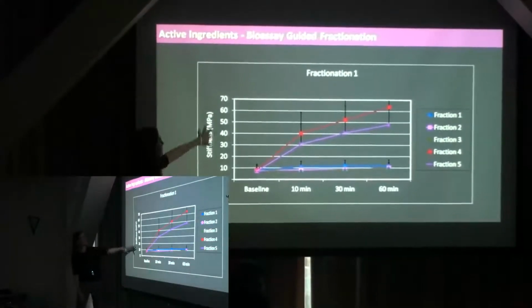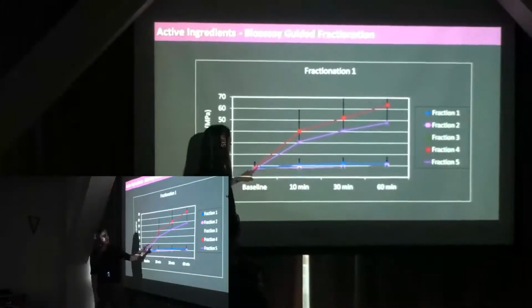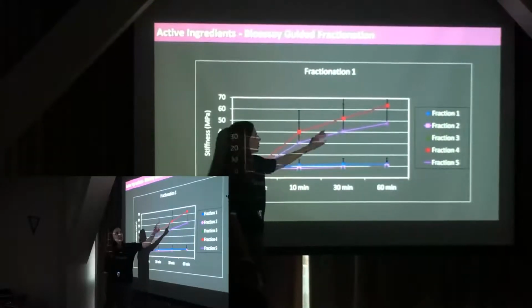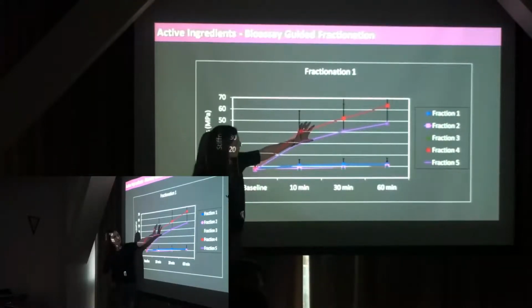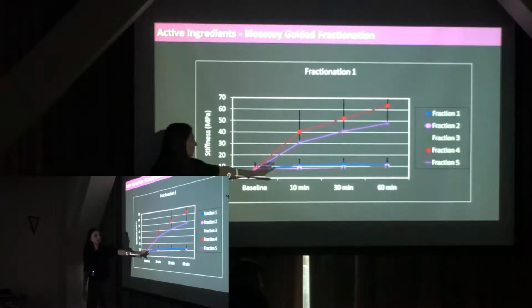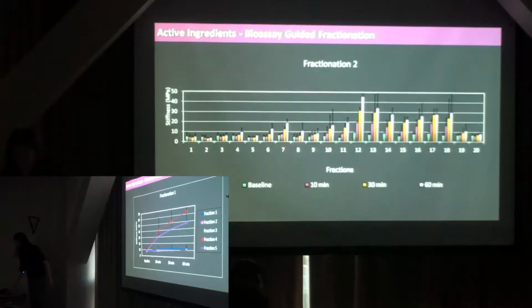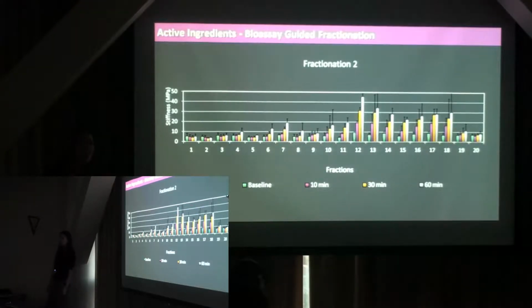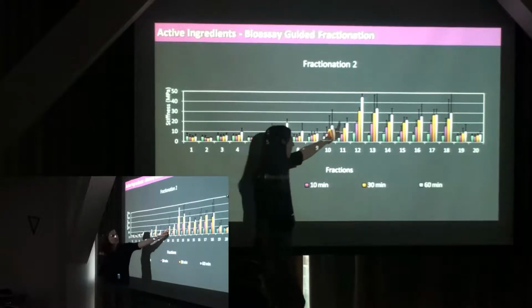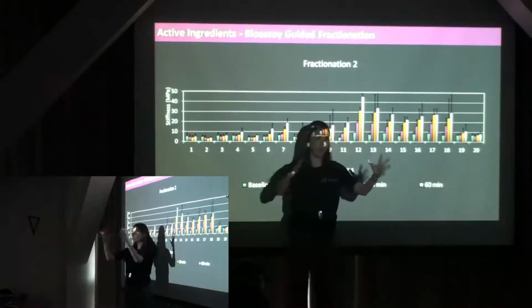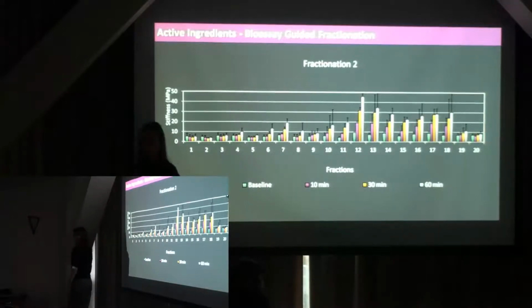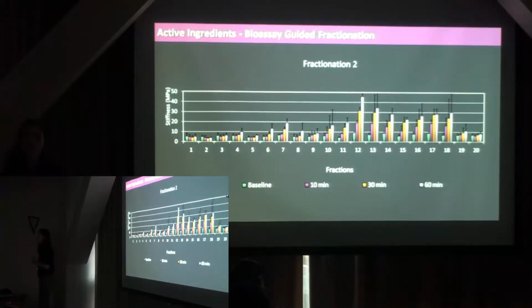This is just an example. Then we use that stiffness method, and we look at different time points, and we look at the stiffness of the dentin. So this guides us. What we did is we got these two fractions at the lower end, fractions 4 and 5. Then we fractionated those into 20 fractions again, and we start seeing where the activity is. Then we get these and we fractionate them again. What we've seen so far is it's not going to be one compound, of course, but hopefully we can get a couple together and maximize activity by concentration, and then we have an intervention material.